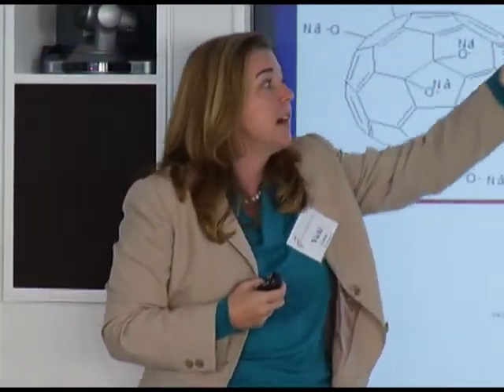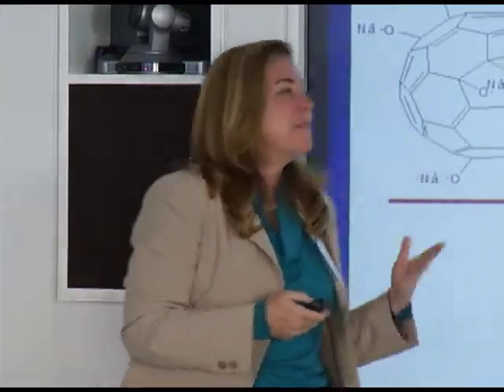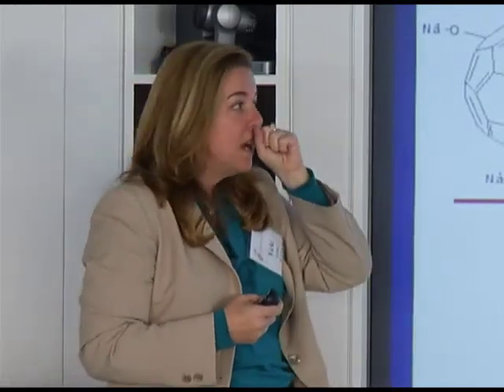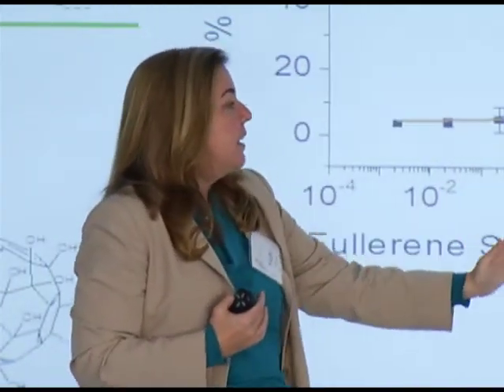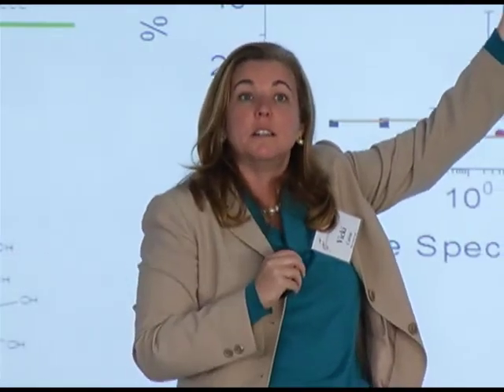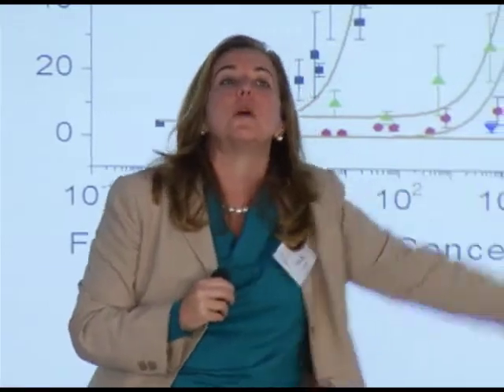So what we did, and this is with Lon Wilson in our chemistry department, is we derivatized our materials to make them more water soluble, which I found counterintuitive. Shouldn't that make them more toxic? But in fact, it made them much less toxic. This is just one example of a 48-hour experiment looking at how many died. At a very low concentration of the pristine material, a lot of them died. And you couldn't go up to high enough concentrations with the water-soluble one to see the same effect. We did the same thing for nanotubes and found that if you want to make a safe nanotube, oxidize it, derivatize it, make it more hydrophilic, more water-loving. Then it dilutes in a very large environmental system and doesn't get concentrated into compartments. So rather than asking whether engineered nanoparticles are dangerous, it's how can we make them safely? And that was one example.